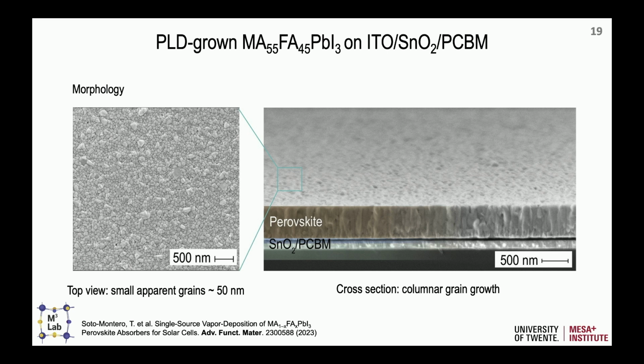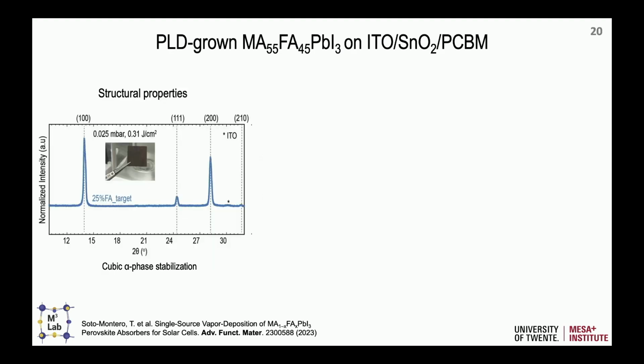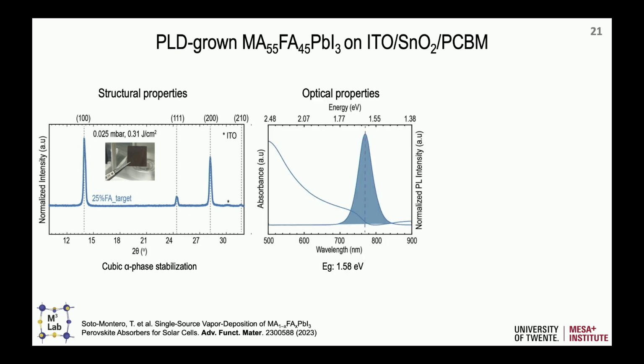This is just a top view scanning electron micrograph of the perovskite as deposited basically in the PLD. And it looks like columnar growth. So it's very similar to how a co-evaporated film will look. Structural properties, so we have basically the cubic phase, and we have very highly oriented films. This is how it will look in the lab. These are the optical properties, so a band gap around 1.58 electron volts, which is expected for this specific ratio of MA and FA, close to 50-50.